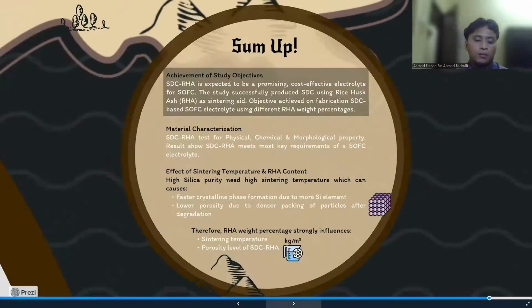In summary, this study demonstrates that rice husk ash silica is a game-changing sintering aid for SDC electrolytes. The study successfully engineered an SDC-RHA composite that hit all three targets. First, fabrication, which uses RHA as a sintering aid across weight percentages, cost effectiveness, and performance, which made the key SDC electrolyte physical, chemical, and morphological structure only, not in terms of conductivity property because of time constraint.